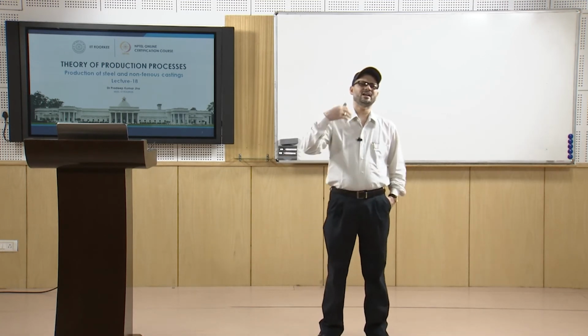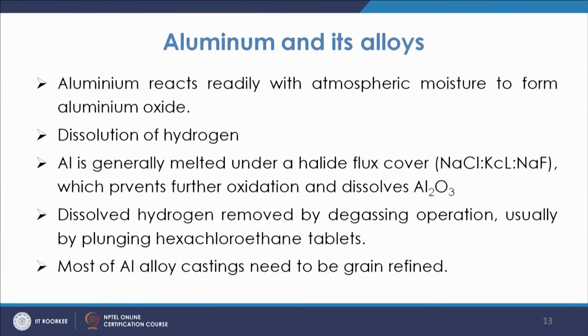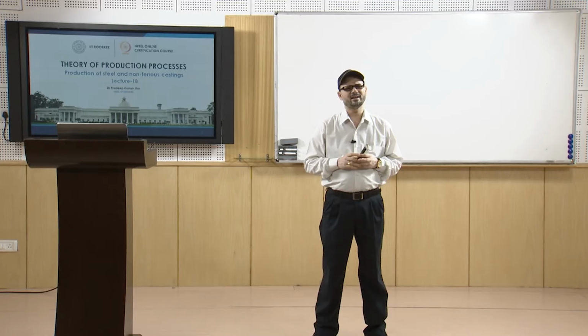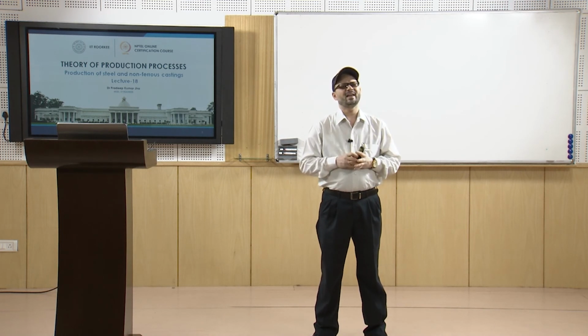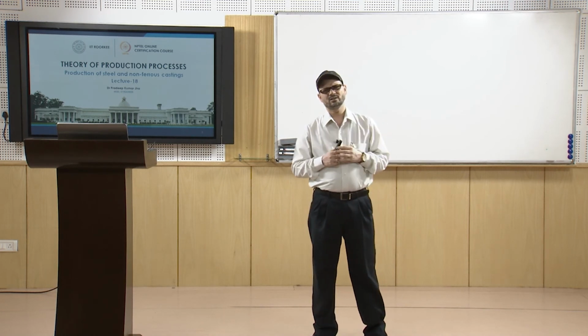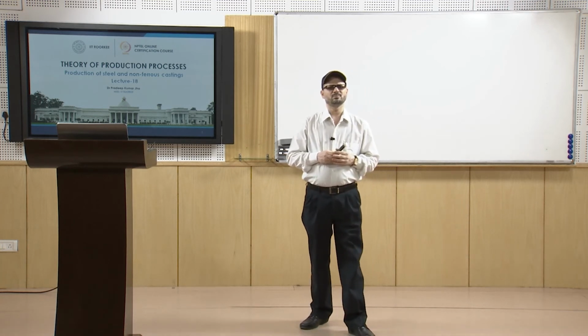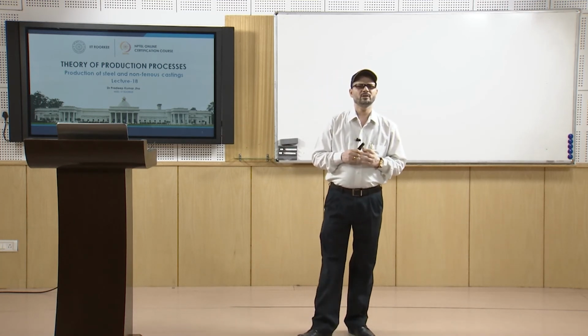Similarly, aluminum, the challenge is that it will react with atmospheric moisture to form aluminum oxide, which is undesirable. So, that needs to be seen, that how can we prevent that. The dissolution of hydrogen is another challenge. So, that also needs to be looked into. For that, normally aluminum is melted under a halide flux cover, which is NaCl, KCl and NaF, and that will basically prevent further oxidation and the dissolution of Al2O3. So, that is another thing which is important in the case of aluminum.